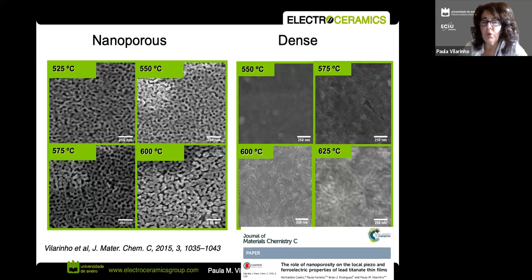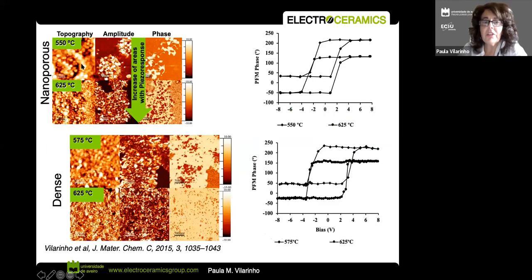So let me show you some of our microstructure. This is in the case of lead titanate. You can see here how they varied with the temperature. Of course, if we anneal them to very high temperature, we will simply destroy the porosity. We make a dense material. But while they are porous, that's what we did. So these are real data.